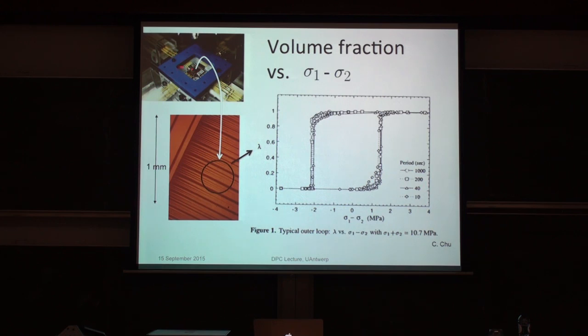There was an example of transforming one variant of martensite to the other. In this case it's an orthorhombic crystal. And this dark red region is one variant of the martensite, and this light red region is another variant. And there's only two variants represented in the pictures. So it's a microstructure consisting of exactly two variants of martensite. And if you play around with the stress in these two axes, you can make it transform. That's how this graph was obtained, by cycling the stress, and it's a biaxial stress in a particular way.